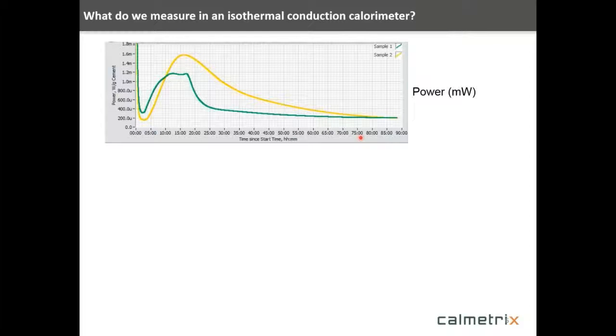So these experiments are very slow experiments. They take place over long periods of time. As you know, the curing of cement is a very long-term reaction. And these instruments are designed to pick up that small amount of heat that gets evolved from the reaction. And typically we're running anywhere from 24 to 72 hours, sometimes longer, with these experiments.